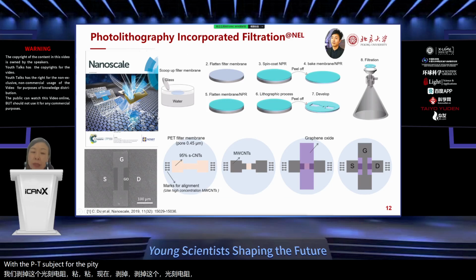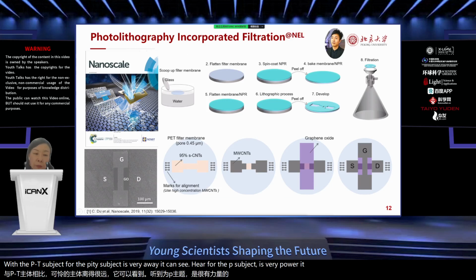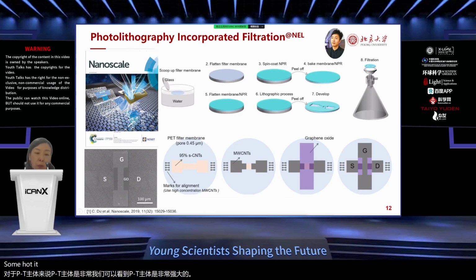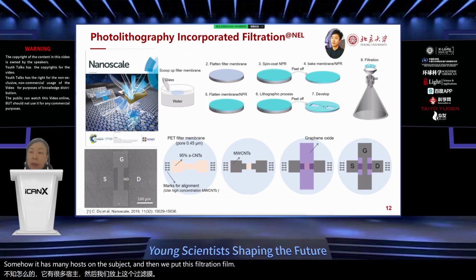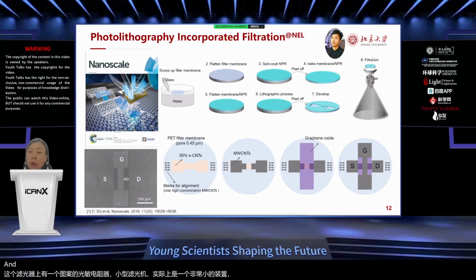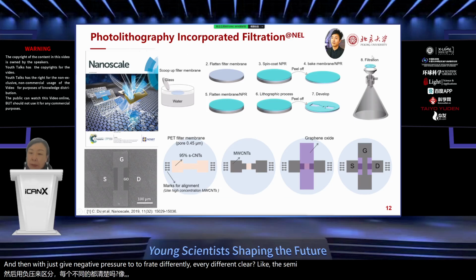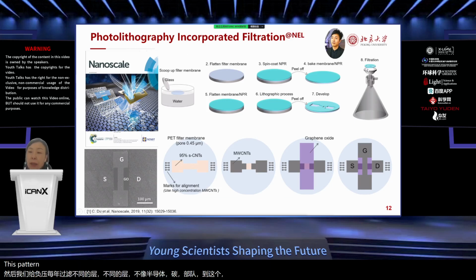For the PET substrate, we can see here it is very porous. It has many holes on the substrate, and then we put this filtration film and the photoresist with the pattern on this small filtration machine. Actually, it's a very small gadget, and then we just give negative pressure to filtrate every different layer, like the semiconducting carbon nanotubes, into this pattern, and then the pattern will be left on this PET substrate.